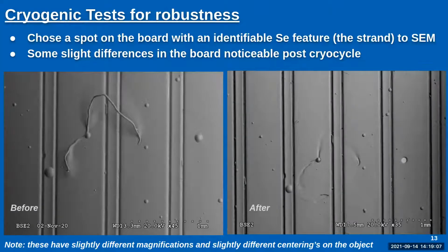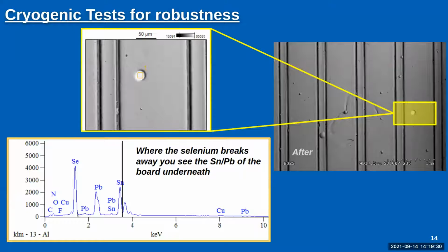We chose a specific spot on the board that had a very identifiable strand there that you could see before cryocycling. The picture on the right is an SEM afterwards. You can see the strand has unfortunately broken off, but the residual is still there. You can also see small deformities that have formed on the board due to the cryocycle. If you then perform this EDAX on them and zoom into those particular substrates, you can see that what's actually been exposed is the tin and lead that makes up the PCB underneath it, the traces underneath it.